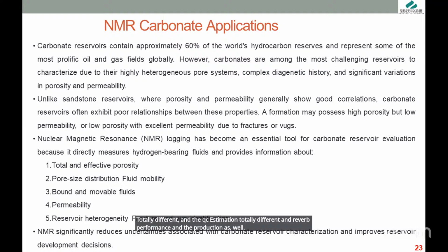Unlike the sandstone reservoir, as we mentioned, where porosity and permeability generally show good correlation, carbonate reservoirs often show a poor relation between these properties. So carbonate is one of the most challenging for NMR. A formation may possess high porosity but low permeability. This is another case for the carbonate, or low porosity with excellent permeability due to fractures or vugs, which count as secondary porosity. As we all know, in sandstone the primary porosity is dominant.